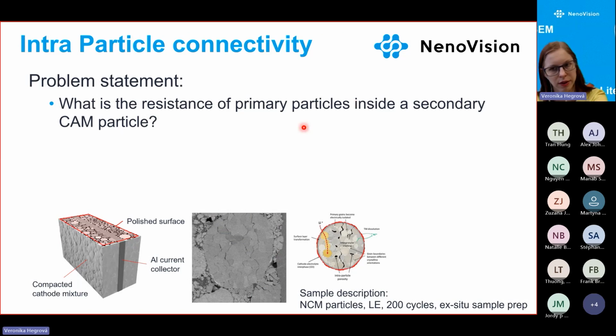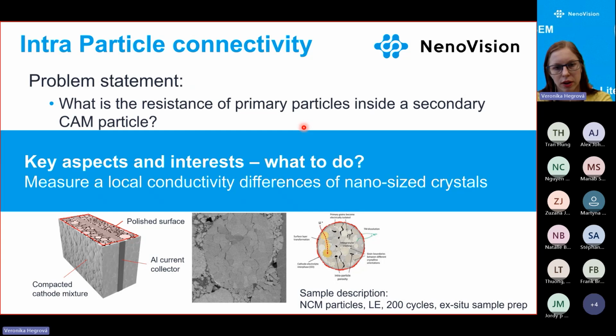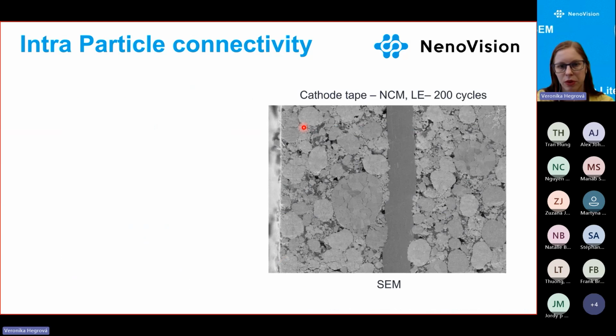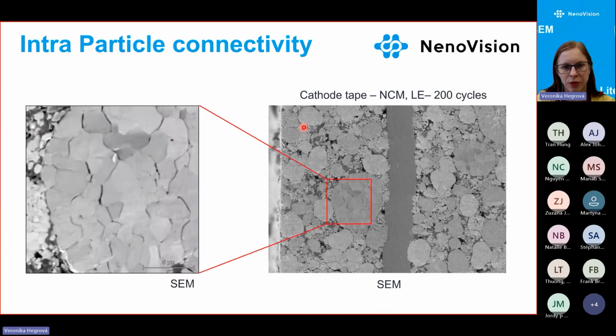Till now we measured on a larger scale. Let's have a look at the inner part of the secondary cathode active material particle. What we need to do, we use the nickel, cobalt, manganese particles in a liquid electrolyte cycled tape, and we need to measure local conductivity differences of the nano-sized particles. So first of all, we localize the structure. What do you see? Intergranular cracks, quite a lot actually.